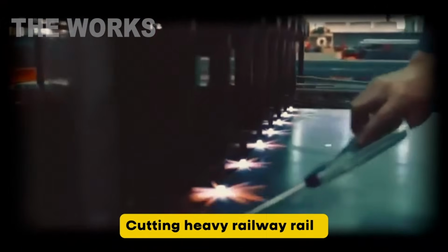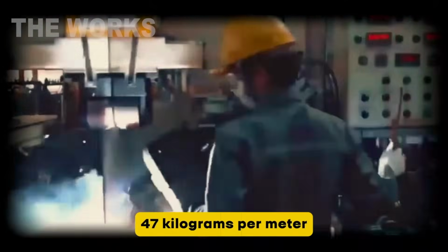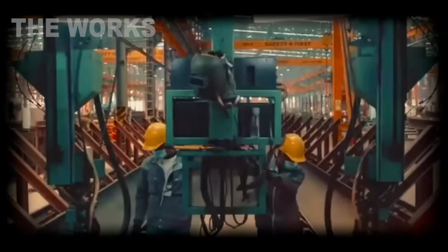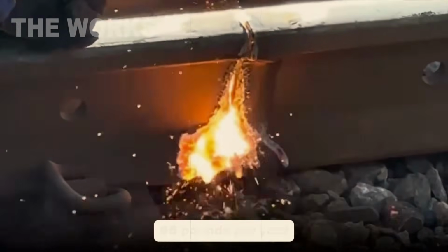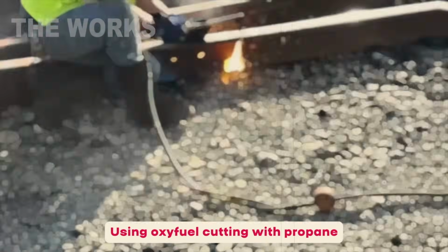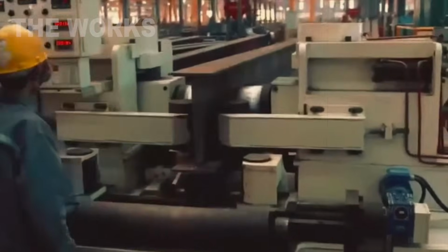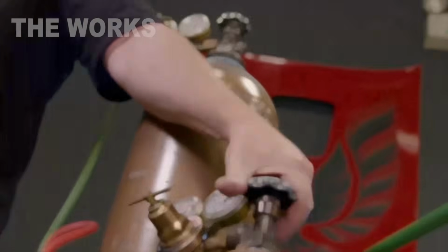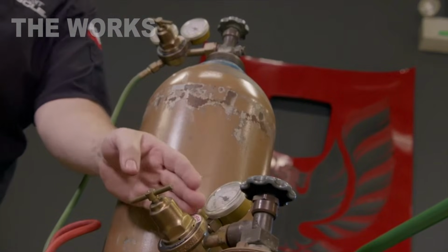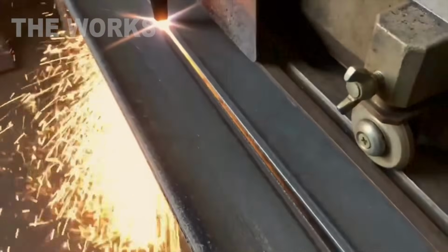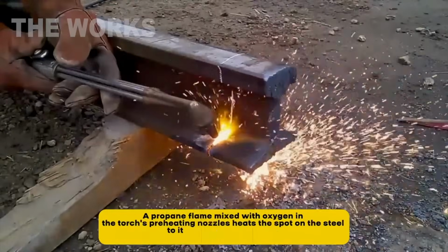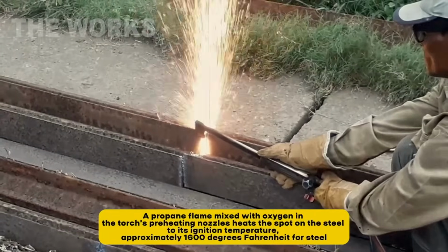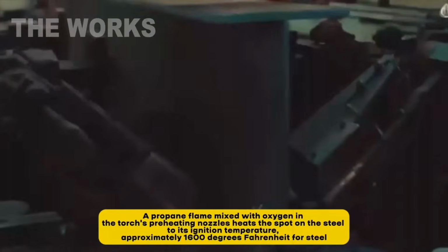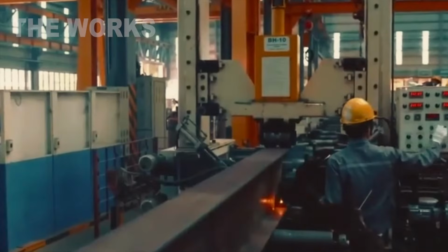We're watching the cutting of a heavy railroad rail, 47 kilograms per meter, which translates to roughly 95 pounds per yard, using oxy-fuel cutting with propane. The oxy-propane torch system operates on a principle that's elegantly simple, yet demands real skill to execute properly. The propane flame, mixed with oxygen in the torch's preheat nozzles, heats a spot on the steel to ignition temperature, around 1600 degrees Fahrenheit for steel. Once that critical temperature is reached, a stream of pure oxygen under high pressure is introduced through the cutting nozzle.